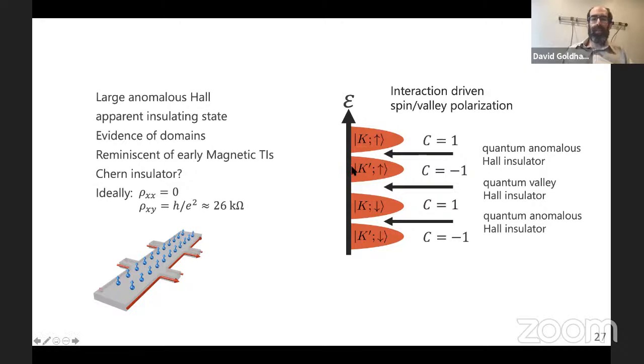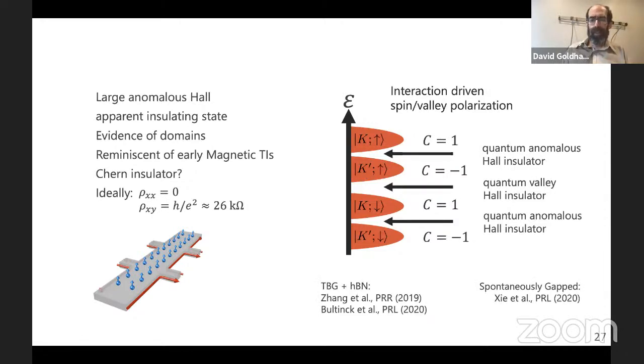And let me say that it was evident to theorists from the start, though it took me a while to be confident of this, that we were seeing valley polarization. And indeed, the first magnet that was built out of little circulating currents of the wave functions, instead of primarily out of spins. Theorists were very clear about that, because if you see an anomalous Hall signal, that can't come just from spin. If you have spin polarization, electrons are not going to deflect preferentially to the left or to the right unless there's spin orbit coupling. And carbon is extremely light, so you expect almost no spin orbit coupling. So having a very strong anomalous Hall signal strongly suggested that there is valley polarization, but not necessarily what's happening to the spins.